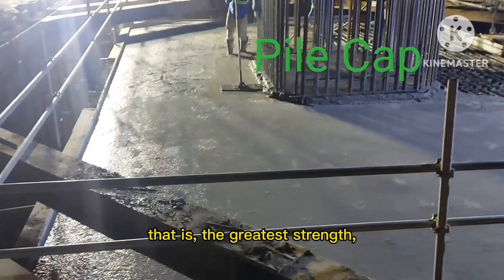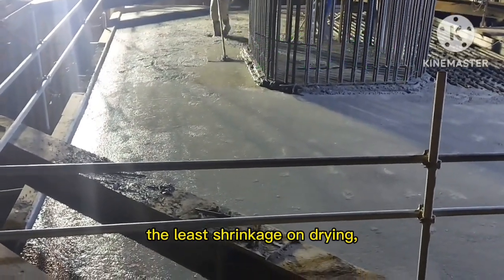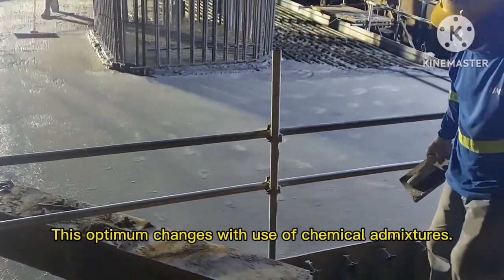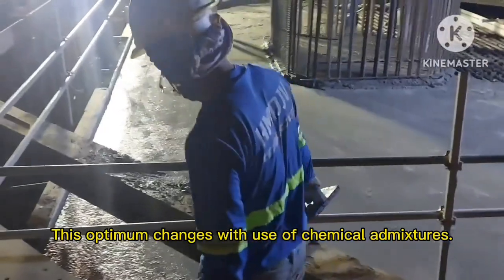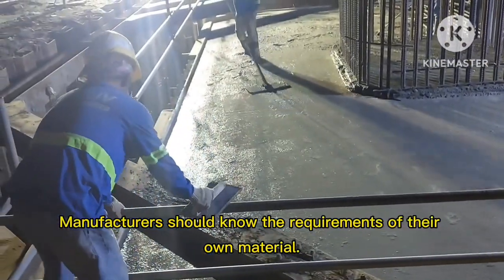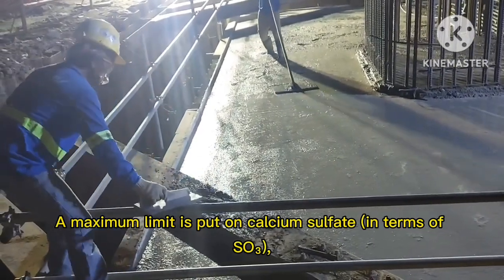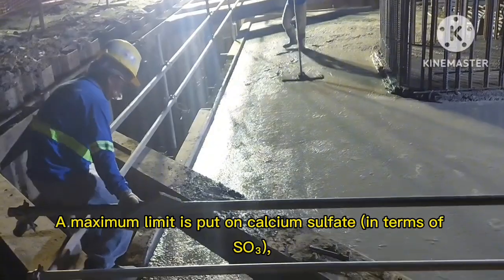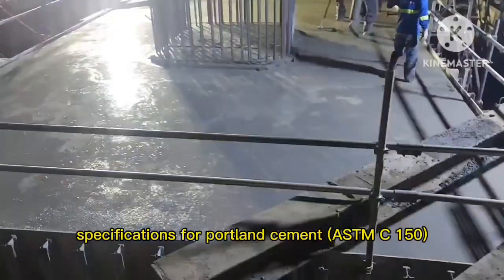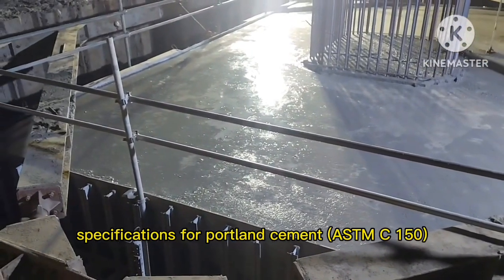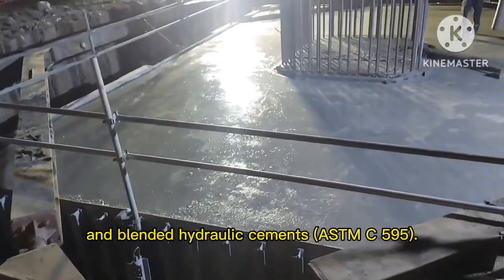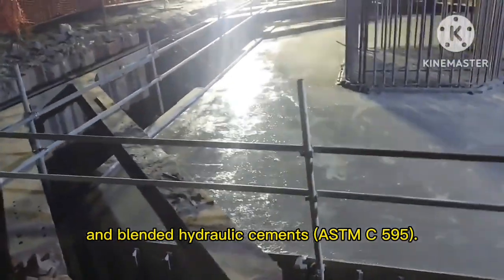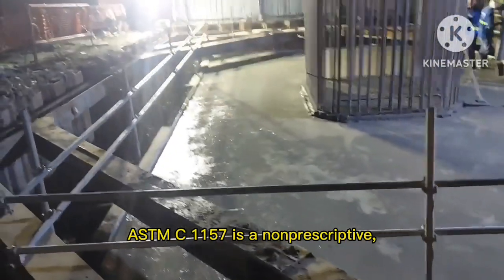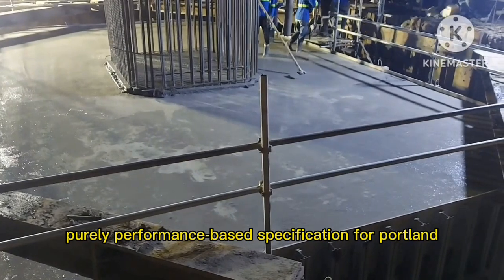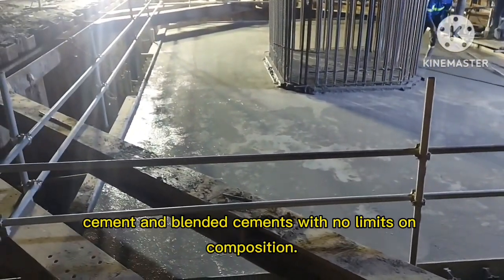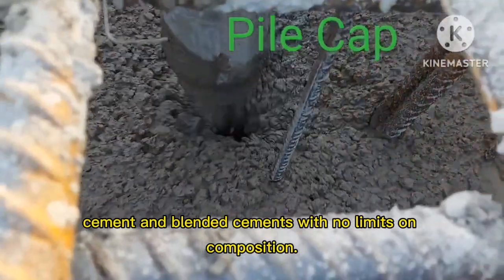That is, the greatest strength, the least shrinkage on drying, and the least swelling on wetting. This optimum changes with use of chemical admixtures. Manufacturers should know the requirements of their own material. A maximum limit is put on calcium sulfate in terms of SO₃ in current prescriptive specifications for Portland cement, ASTM C150, and blended hydraulic cements, ASTM C595. ASTM C1157 is a non-prescriptive, purely performance-based specification for Portland cement and blended cements with no limits on composition.